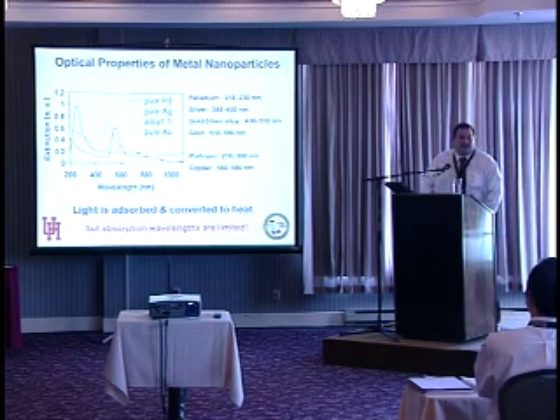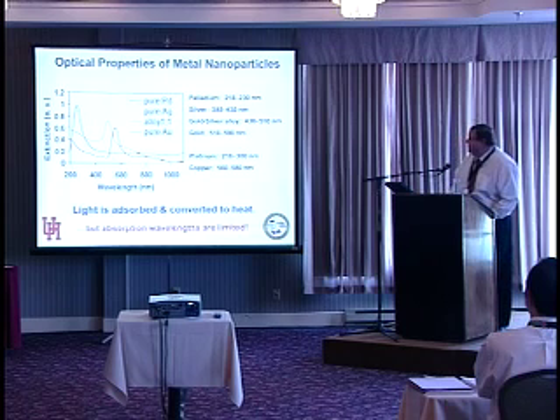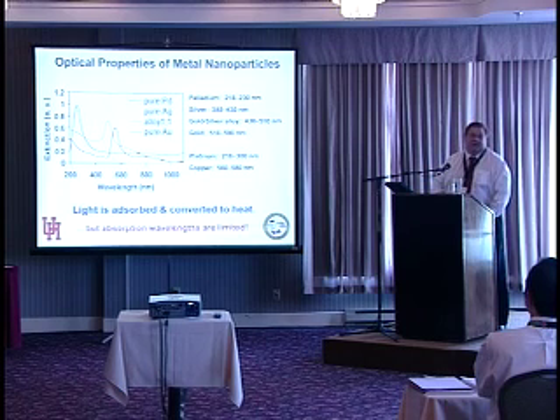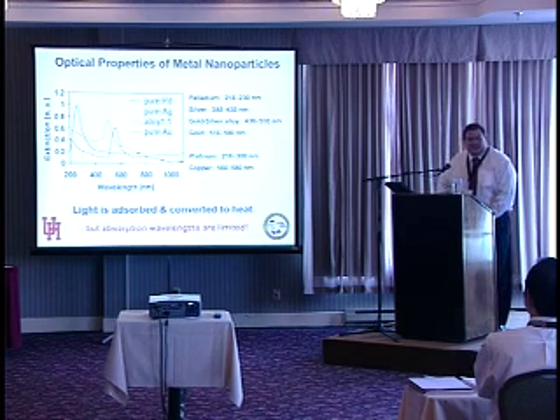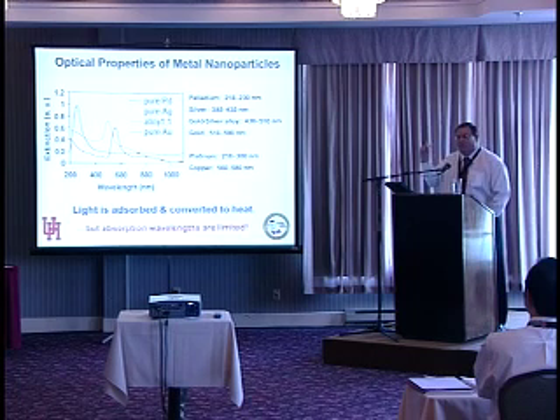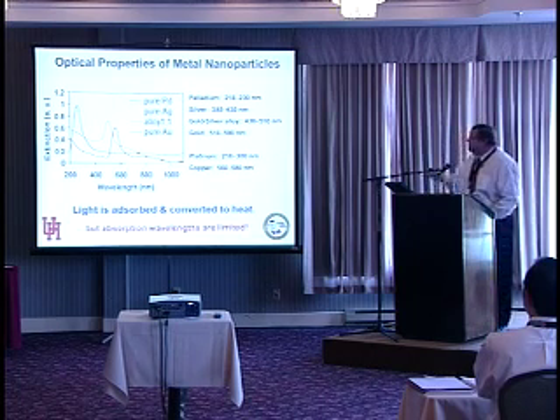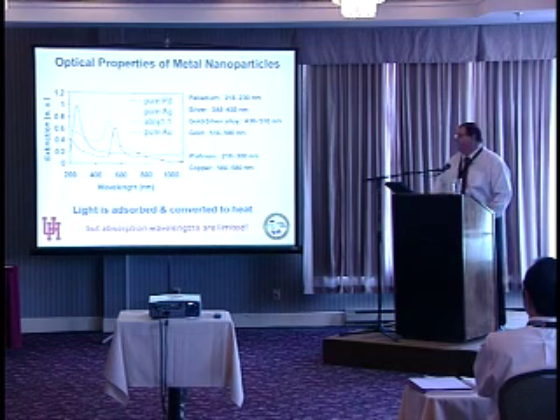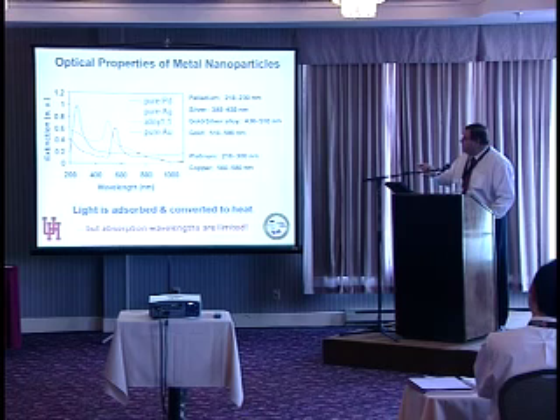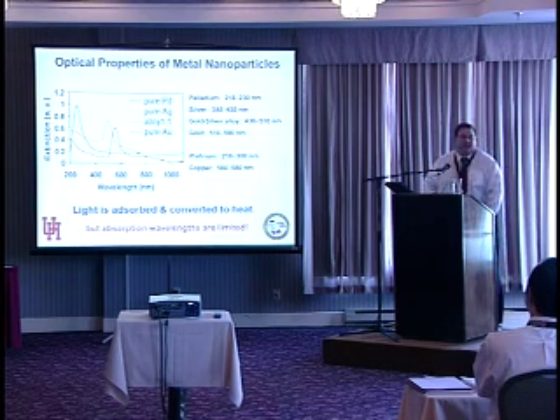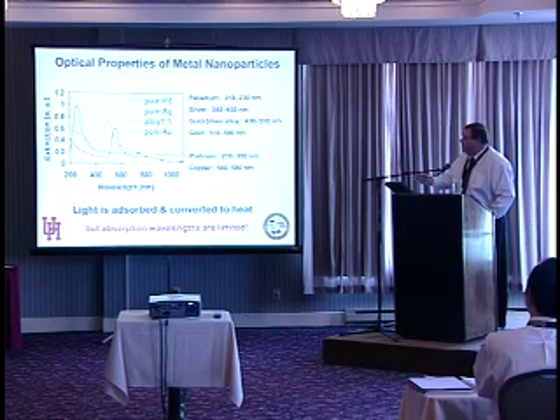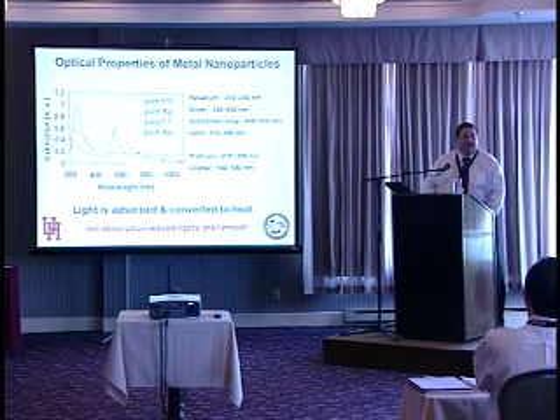My group, on the other hand, is interested in something that is arguably much more boring from the optical point of view. And these are just simple metal nanoparticles. Many of you might be aware of gold nanoparticles, for example, that have been used for centuries in stained glass. So the beautiful reds that you see in stained glass has come from the optical absorption, the plasmon resonance of gold nanoparticles. So what happens with metal nanoparticles, like gold, silver, palladium, and copper, is that the light is absorbed and converted to heat. So unlike semiconductor nanoparticles, these nanoparticles will absorb light and get hot, okay?